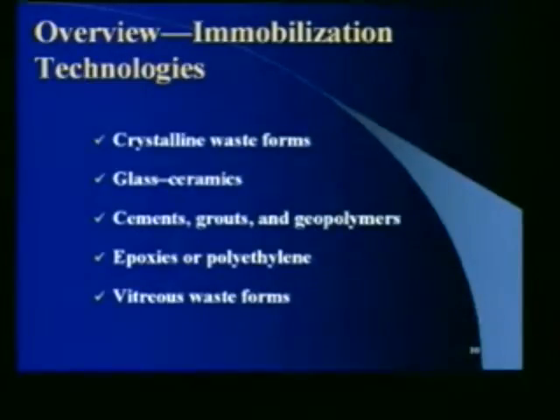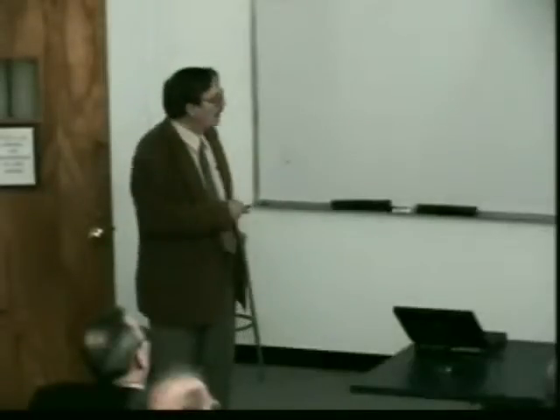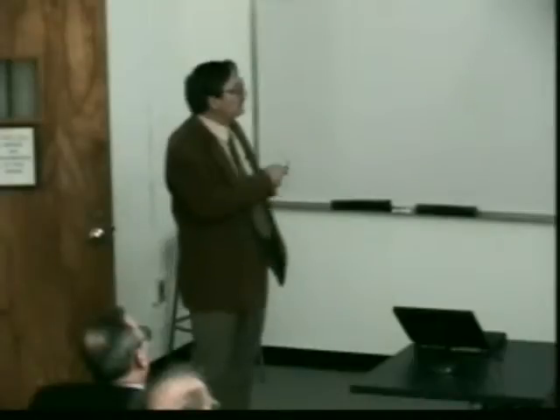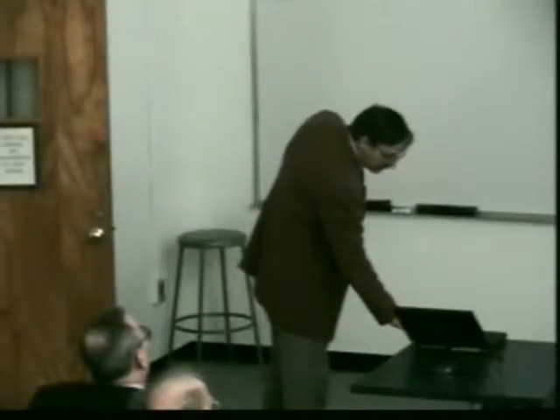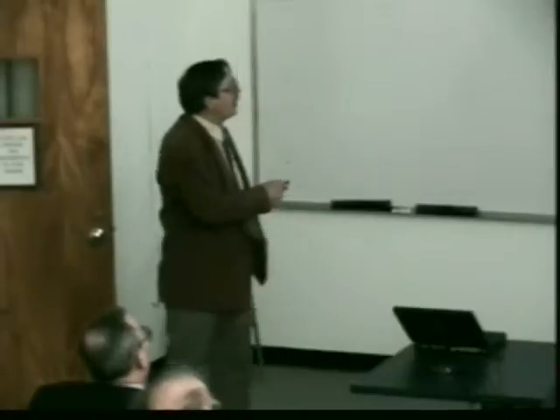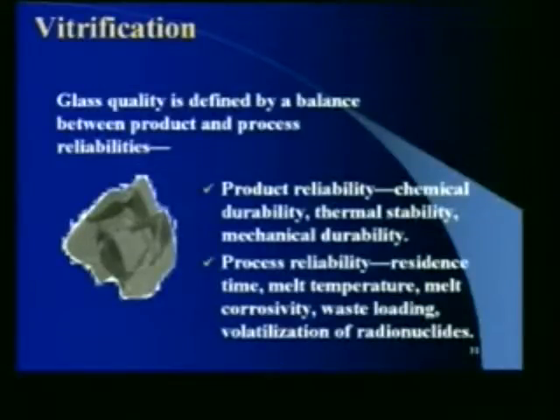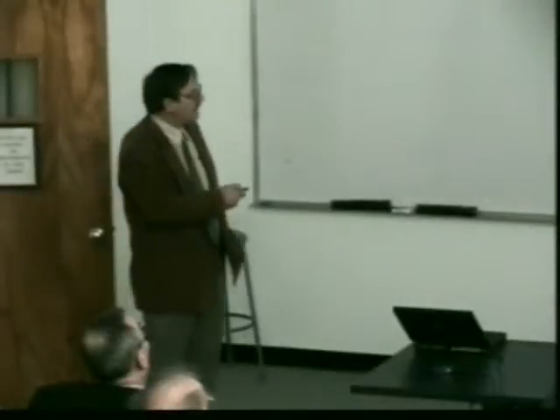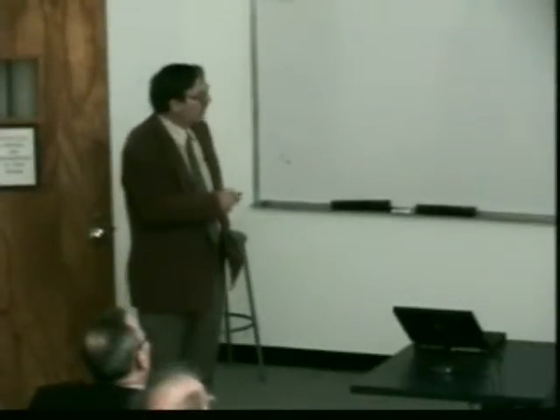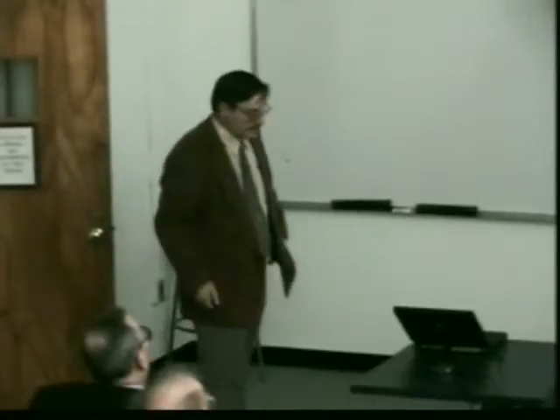All of the vitreous forms that are made by joule ceramic heating or plasma or so on are really the type we're talking about here, although these others have some real potential in certain applications. So the glass quality is defined by a balance between product and process reliability. Again, what we like is chemical durability, thermal stability, mechanical durability. But the processing depends on residence time, viscosity, waste loading, melt temperature, corrosivity, volatility, those things that we were talking about before. So developing processes that allow us to make a reliable product that also take into account the processing considerations is very important.